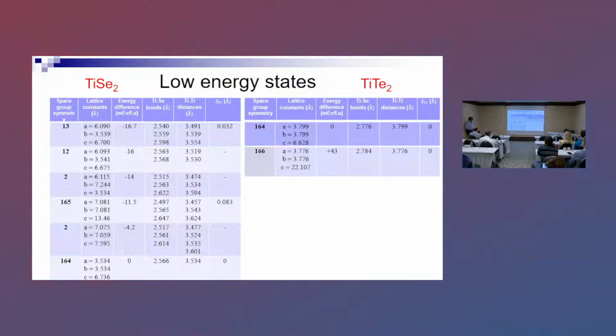That was the main point, to investigate if you have a semiconductor state. So, in the case of titanium ditelluride, we see that the lowest state is this 164. This is exactly the disordered state, and no low energy metastable state.